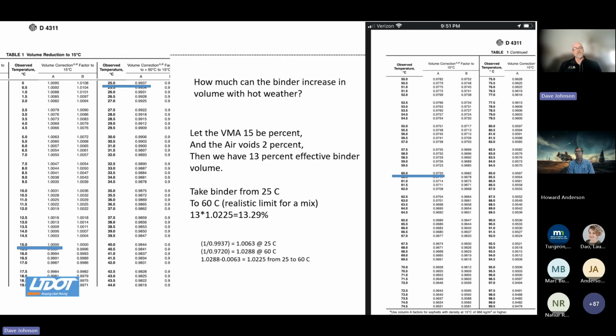Howard talked about the flushing issue. The details of this slide are more than what is necessary. The bottom line is he did some calculations to verify that even at those low air void volumes, there would be enough room in the expansion of this material in the heat of the summer that we would not experience flushing. And the upshot is that there was adequate room, and we indeed have not seen flushing in the field.